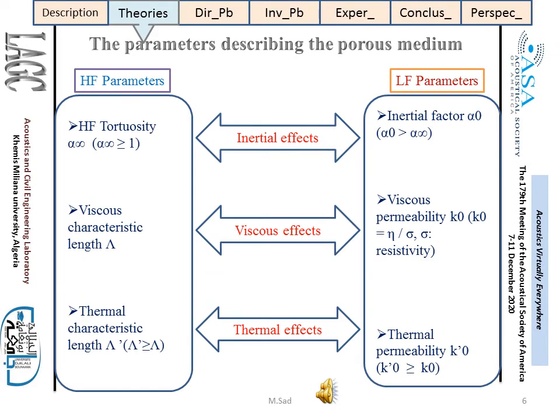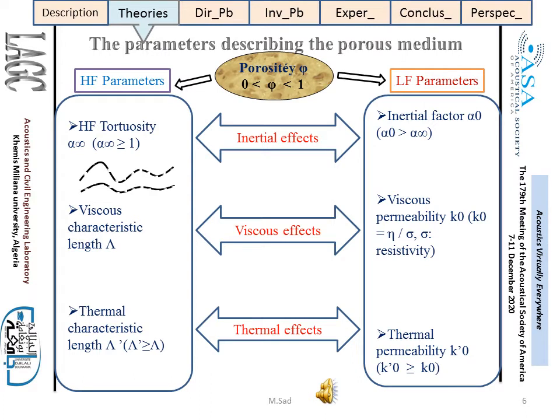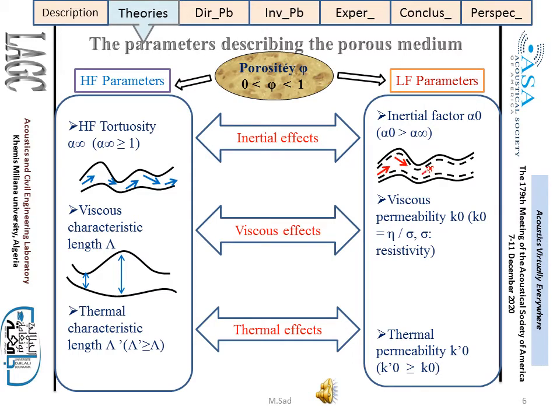There are several acoustic parameters describing porous media. These parameters can be divided in two categories: high frequency parameters and low frequency parameters. Porosity is the key parameter informing us about the proportion of fluid in the porous material. It presents the ratio of the volume occupied by the fluid to the total volume occupied by the medium. According to the Johnson-Champoux-Allard models, the high frequency parameters are the high limit frequency of tortuosity and the viscous and thermal characteristic length. The low frequency parameters are the static tortuosity alpha 0 and the viscous and thermal permeability.